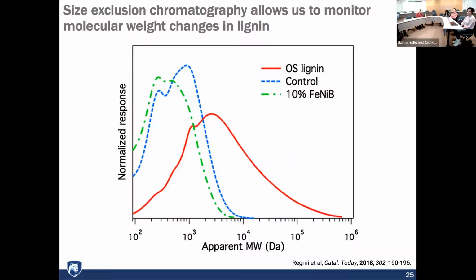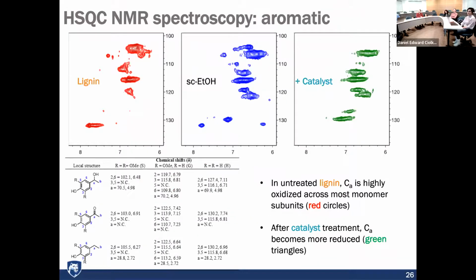And here we have maybe 1,000. So this response tells us how many, and this one tells us how much does it weigh, right? So you could think of it like a histogram. Most of them weigh something like 3,000 grams per mole. But when we do catalysis, we see that the molecular weight changes. What comes out is material that has a lower molecular weight. Now, most of them have a molecular weight of even less than 1,000, maybe 800. Some here, this is probably 200. So the molecular weight goes down. And when we add different catalysts, we see different distributions. Right? So our catalyst is changing the molecular weight of the lignin, but it also changes, remember, we're interested in